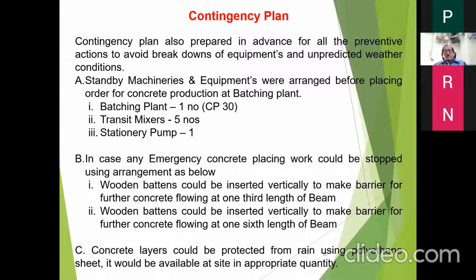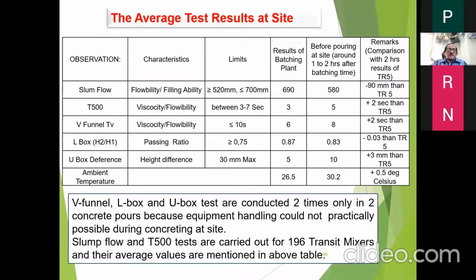But if an unfortunate event happens, how do we stop the concreting? By inserting wooden battens, and they have to be inserted vertically, so the joint has to be vertical, so that thixotropic gelling would not be there. But if the concrete flows to a distance in a small thin layer, then it would be difficult. Concrete layers could be protected from rain using polythene sheet, etc. So those are normal things.